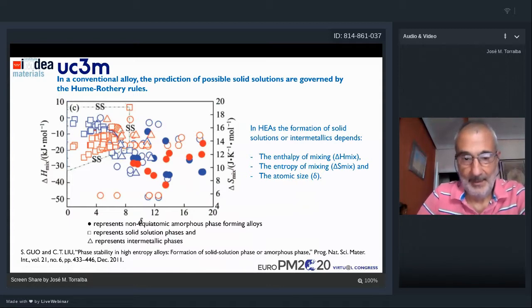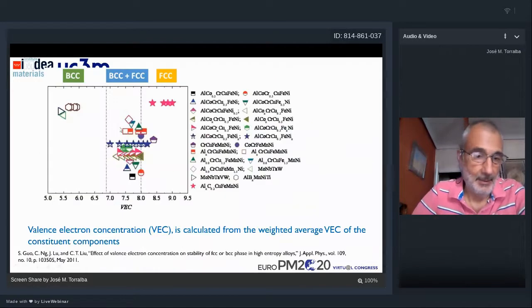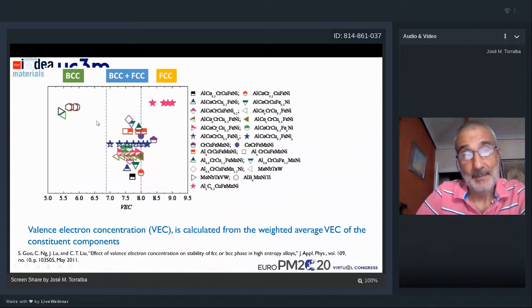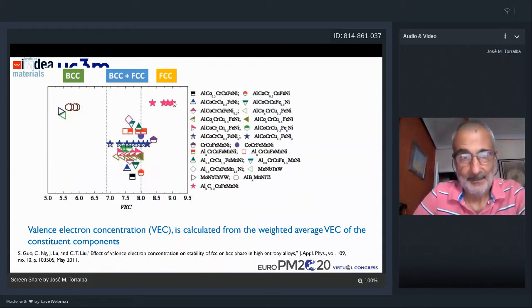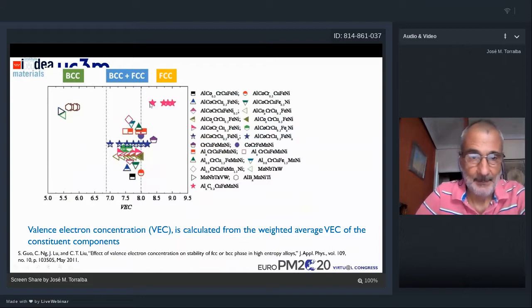So even if you consider other conditions like the valence electron concentration, you can predict if this single phase is BCC or FCC. Most of the high entropy alloys belonging to the transition metals are usually FCC and sometimes FCC plus BCC, and the refractory metals tend to be in the BCC corner.